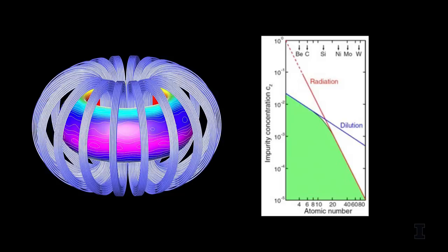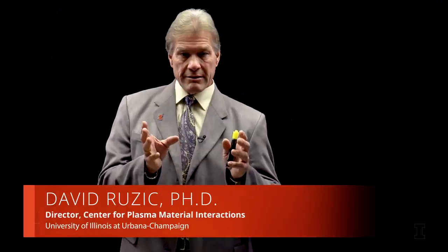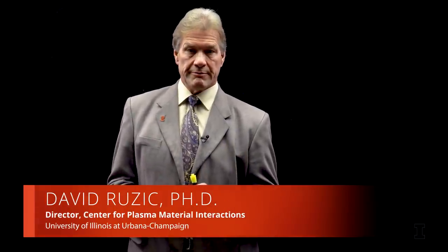If you make it out of something like tungsten, very high Z, you have huge problems when the heat hits the wall because you can only tolerate a tiny amount. But if you make it out of something low atomic number, like lithium, you can see that you could have quite a bit in your plasma and it would work. The low atomic number is not the only reason to use lithium.